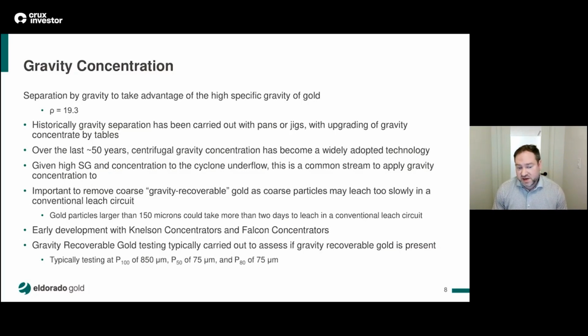Gold particles that are larger than 150 microns need to be removed so that there's enough time for them to be leached. In a conventional leach circuit, they would still pass through to the tailings without being leached. But gravity recoverable gold testing is carried out to see if gravity recoverable gold is present and whether it should be incorporated into the flow sheet.